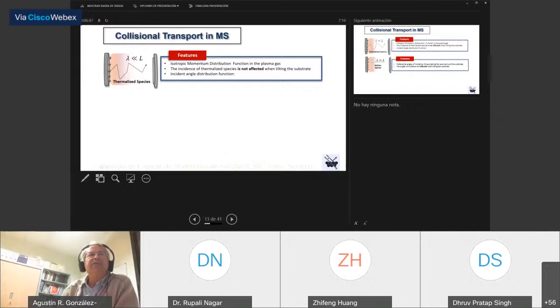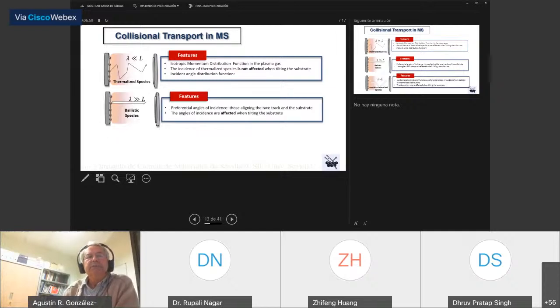In magnetron sputtering, we have three different types of particles: those which can be considered completely thermalized and arrive at the substrate according to an isotropic momentum distribution. We will have ballistic particles, which do not change their trajectory, and these are typically used for glancing angle deposition. And we will also have particles which are partially thermalized and still preserve some of the momentum distribution that they have when they originate in the target. Actually, these two particles are those which are responsible for the oblique angle deposition structure that we are interested in.